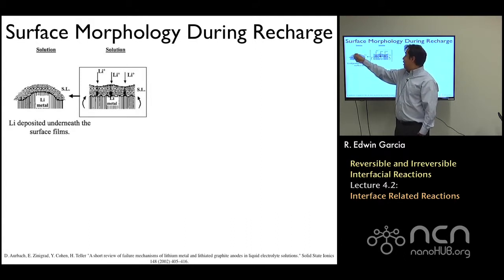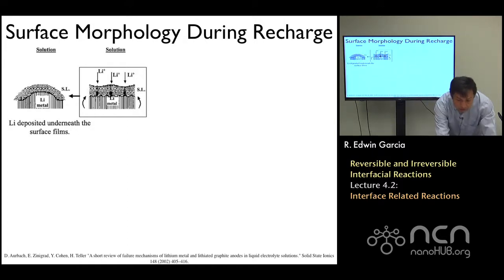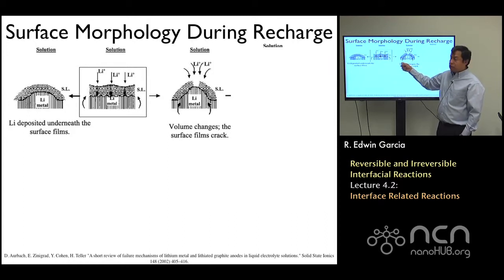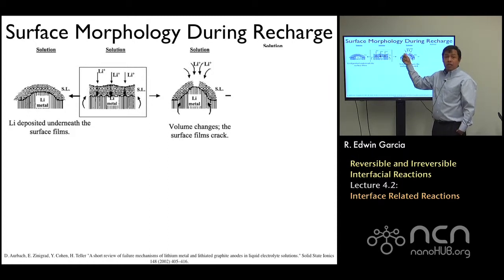But again, this SEI layer, because of its complex morphology and chemistry, can be very brittle, and when that happens, it could open up some gaps. At least that's what is hypothesized. It changes the homogeneity of the reaction, favoring some regions to react with respect to others, and the SEI layer crust will allow easier diffusion through the open areas.